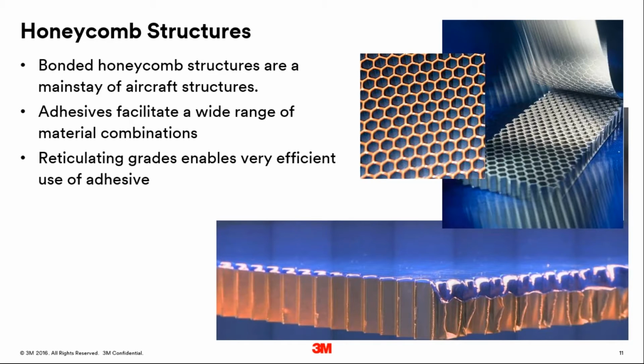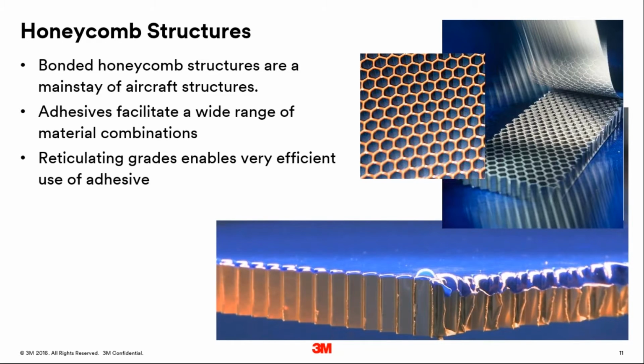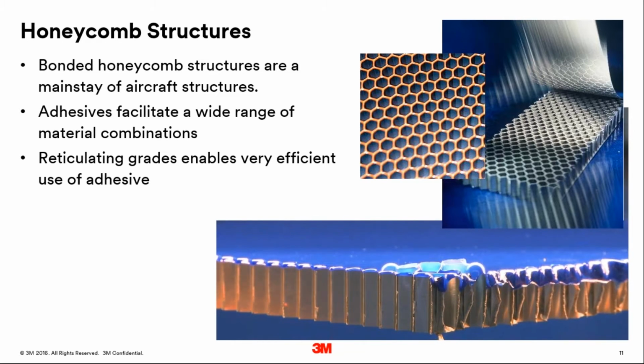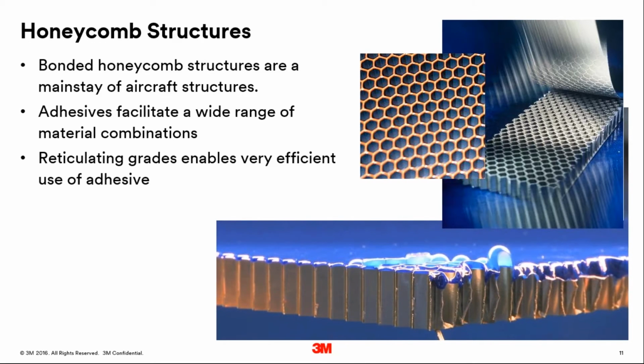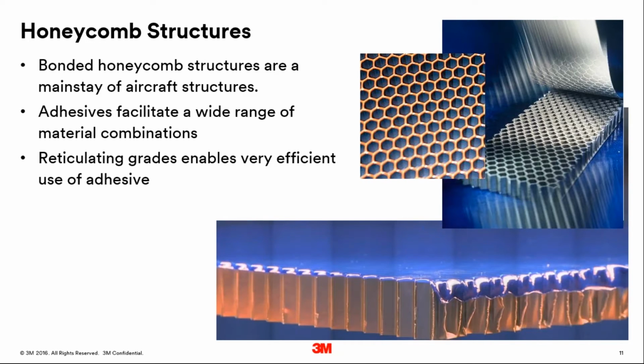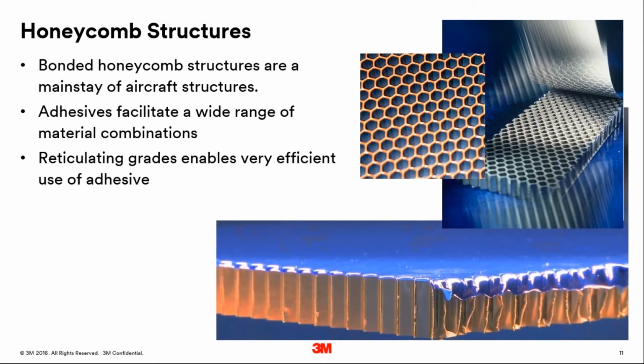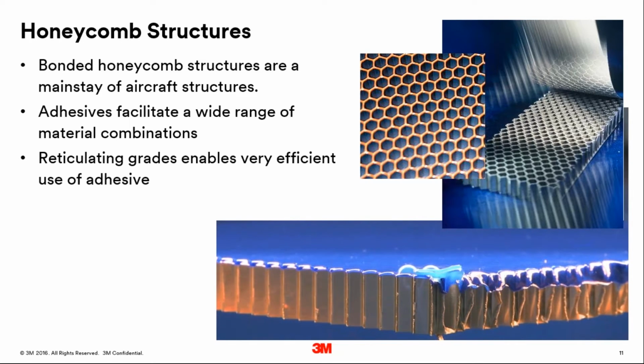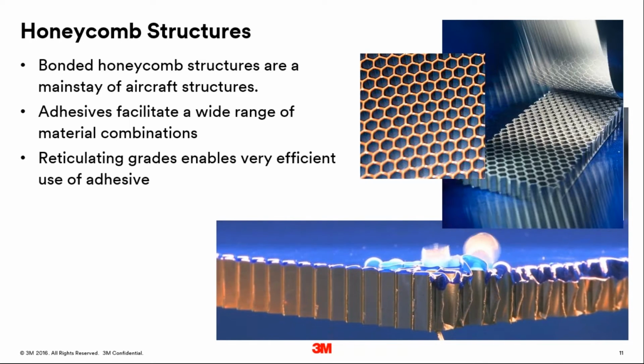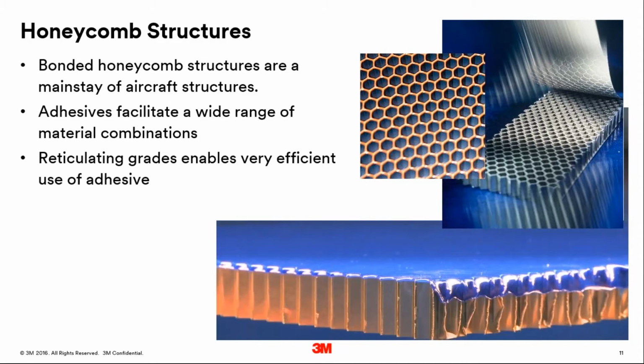So we've developed reticulating grades of adhesives and you can see that simulated down in the bottom right hand corner where we're blowing air through the molten adhesive or softened adhesive so that it coats the edges of the honeycomb and it creates a filleted joint with no redundancy of the adhesive in the holes in the honeycomb.